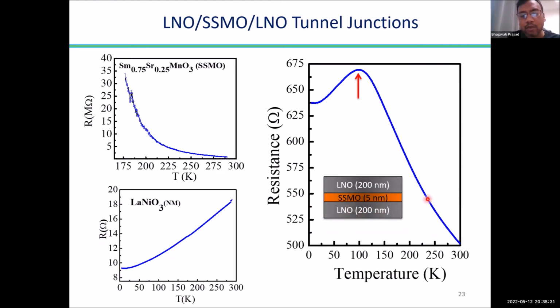What you see is that the resistance is first increasing weakly with decreasing temperature. I say weakly because the resistance goes from 500 to somewhere around 670 when decreasing temperature from 300 to 100 Kelvin. If it were an insulator, the resistance would increase quite fast. And then when you go to low temperature below 100 Kelvin, you see the resistance going down, and somewhere here it becomes flat.